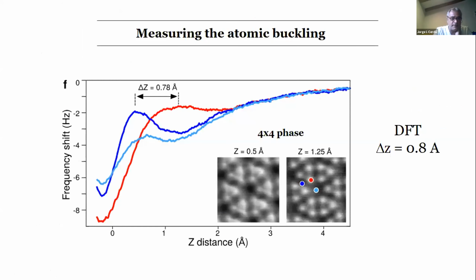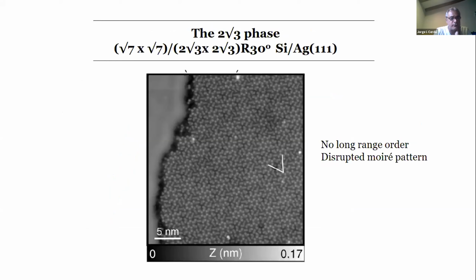Most importantly, what they tried here experimentally is to try to measure directly the buckling. So what they were doing is this frequency shift as a function of the distance, and what we found is that we could identify a bump as we came close on top of one atom or the other. Okay, so what we associated this distance between the two bumps is precisely with the buckling. As you can see here, we are obtaining a distance of 0.78, which perfectly correlates with the DFT. So this is a kind of benchmark that seems that things are working, and with this technique, we're going to be able to obtain the buckling between the different silicon atoms.